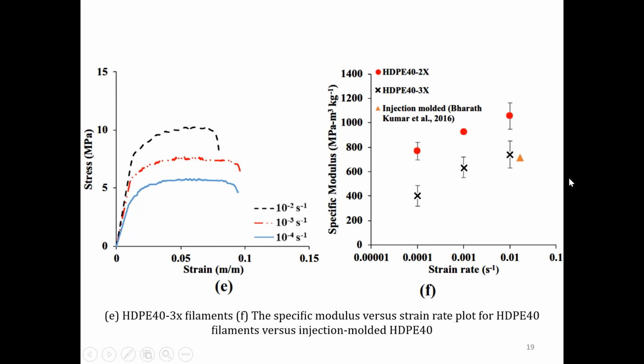So before 3D printing, we compare the filament, I repeat, filament, with the injection molded completely dense dog bone sample. And we check how the performance is, because we don't want to waste the time of the student, nor the machine time, nor my time. Before going to 3D printing, we check whether that makes sense, and we compare the injection molded sample with the filaments. If the filaments are doing good, only then we jump into 3D printing.